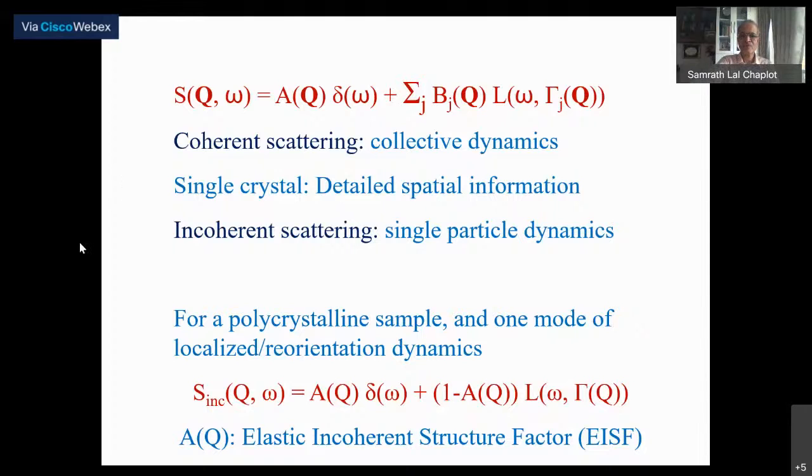So such detailed information was actually obtained using a single crystal of ND4Cl, a deuterated crystal. Though one is getting the single particle dynamics only, with a deuterated crystal one could get the detailed geometry of the reorientation process and so on. We will not go into that kind of detail. Nowadays, most of the scattering, as I said, is on hydrogenous samples, studied using the incoherent scattering of the hydrogen atom, even partially deuterating a sample so that you can selectively look at a molecule.